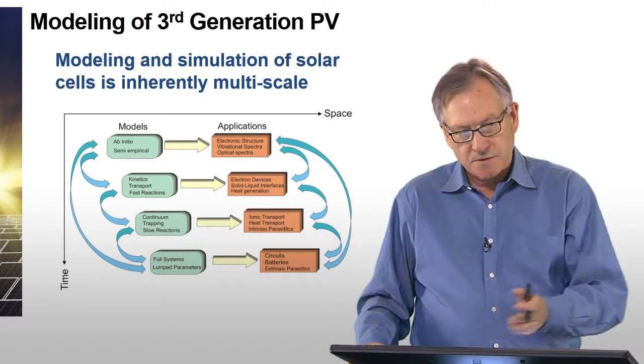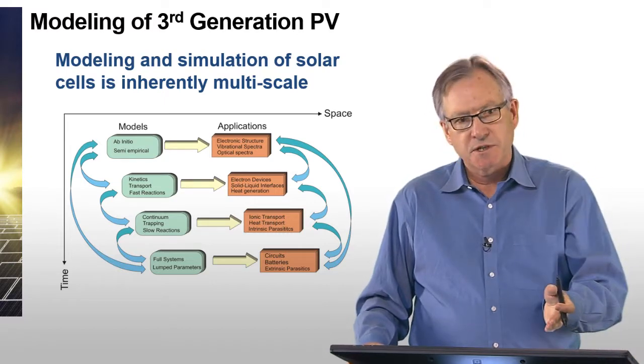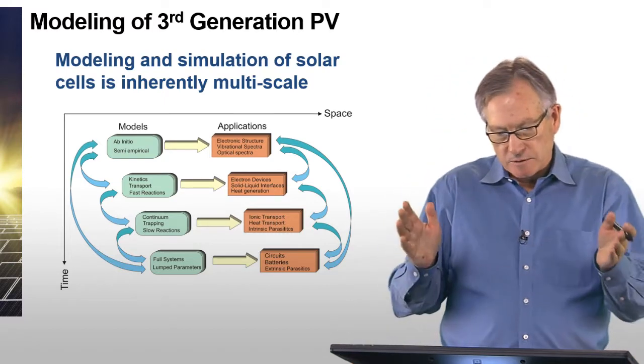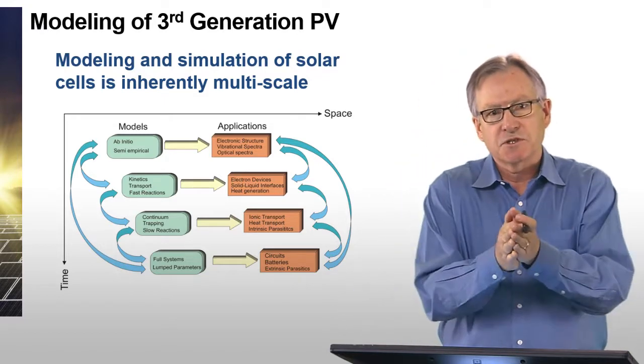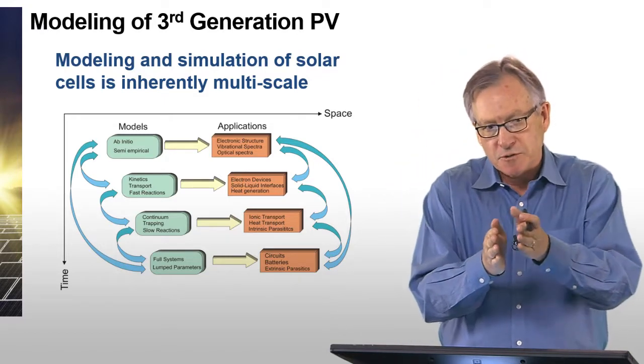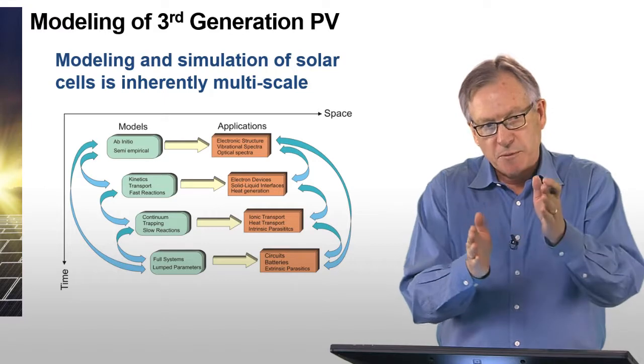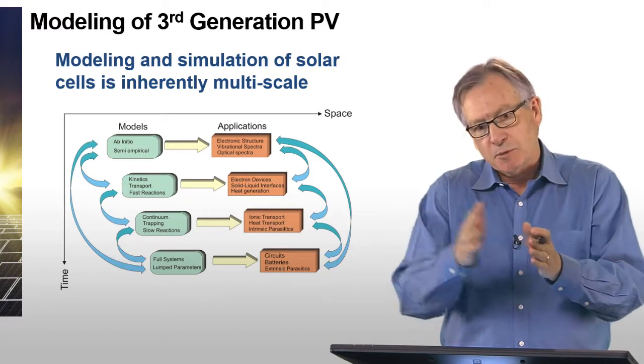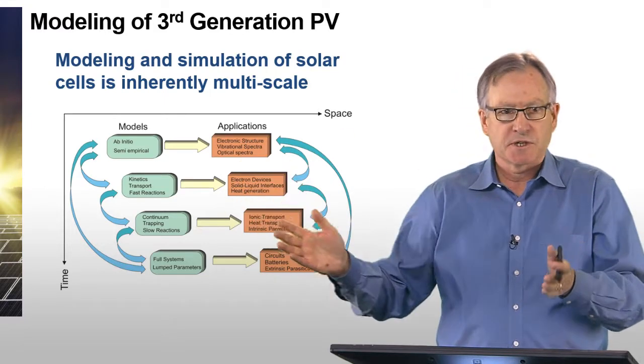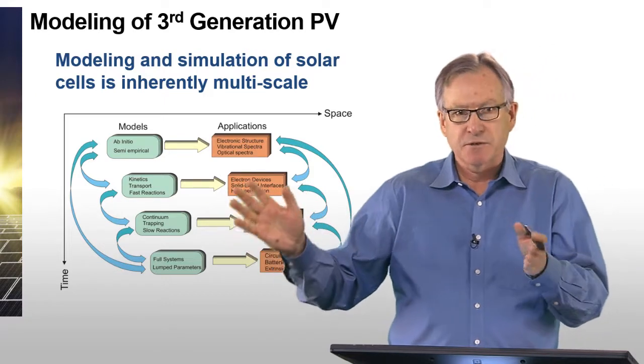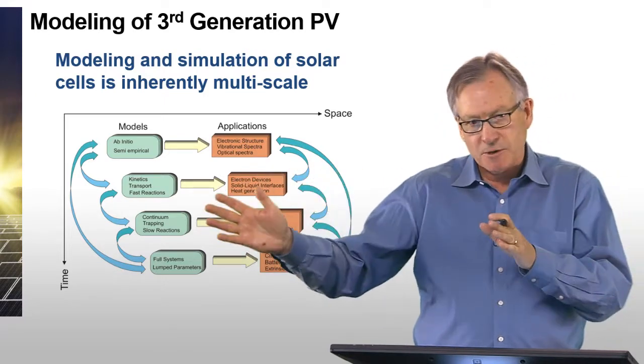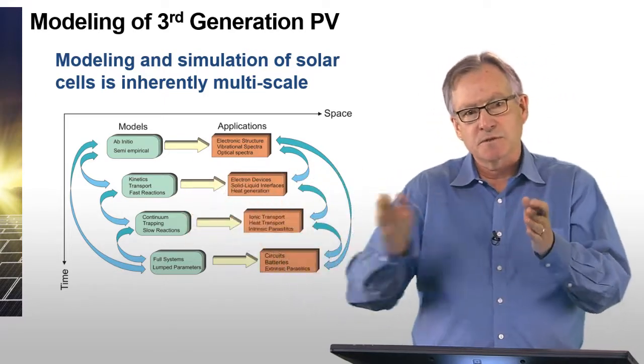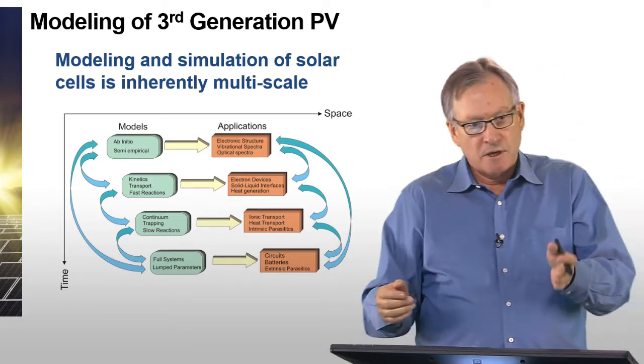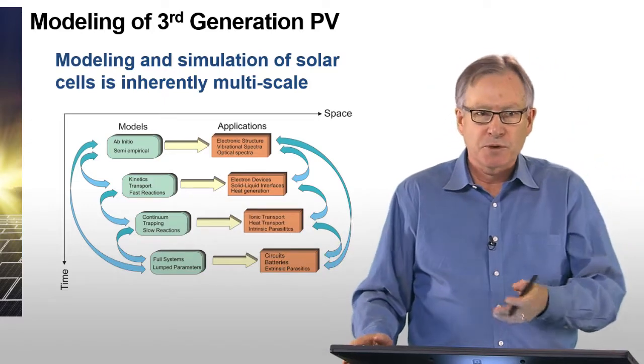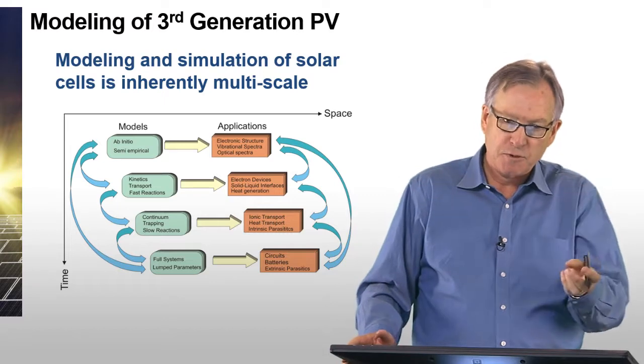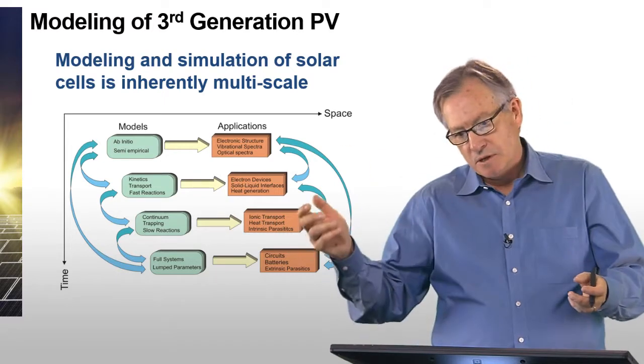And then, of course, you have different distance scales. So you may have a nanostructured cell in which transport within the nanostructure occurs over a few nanometers of dimension, but the rest of the cell is several microns thick. And so you have distance scales that are tens of microns, even hundreds of microns in silicon cells, compared to a few nanometers. And so therefore you have to resolve both very short length scales and very long length scales.